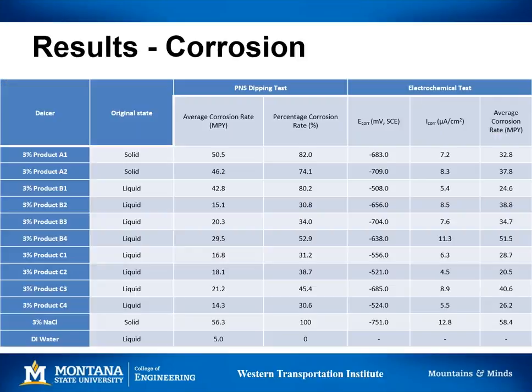So what did we find? Well, now again, remember, this is all relative to the corrosion rate of salt brine. So you can see here that the percent corrosion rate for the PNS dip test for salt brine is normalized at 100%. And so you would hope that all the products would have a lower corrosion rate than the salt brine. And again, these products were tested at a 3% concentration, and that's just the standard practice for these tests. So when you compare them to the salt brine, the complex chloride mineral-based products had lower corrosion scores, which is great, but they're still pretty high.